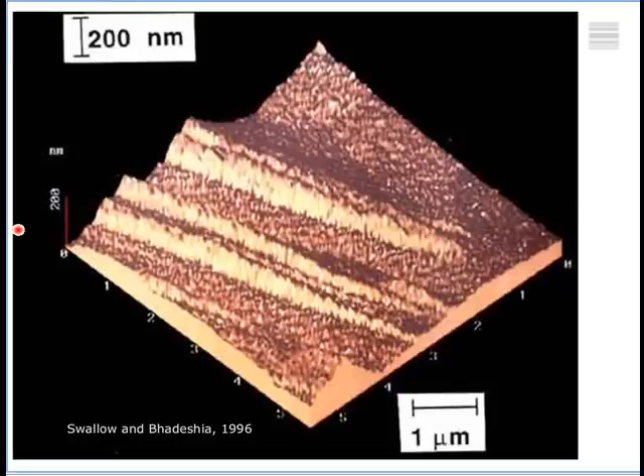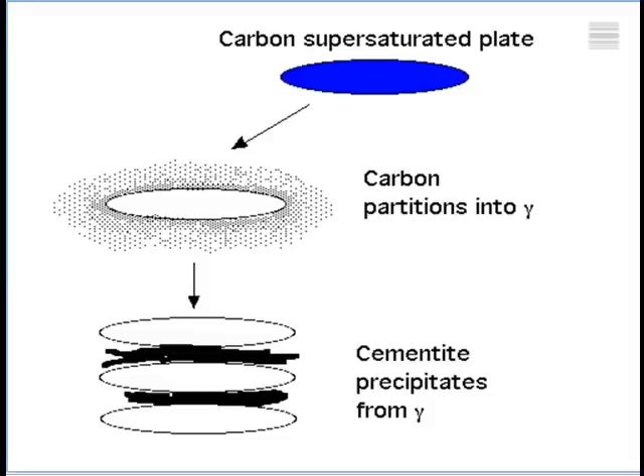If I summarize about 30 years of work on the mechanism of the bainite transformation, then it's very, very simple. All good theories are very, very simple. Okay? So imagine that bainite forms exactly like martensite, that there is no diffusion at all. The carbon is trapped inside the bainitic ferrite. But you are forming it at a high temperature, so the carbon then escapes into the remaining austenite, and then it precipitates as cementite. So this is the classical structure of upper bainite.